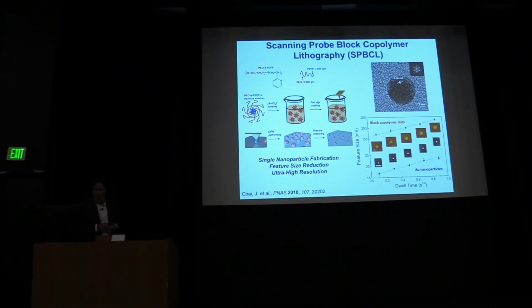If that's hydrophobic, so we can control the type of substrate we use, it will bead up in the form of a reactor that literally has attoliters or less of volume. And then we can treat under reducing conditions, either plasma or heating, as you're going to see, under a hydrogen atmosphere at high temperatures. Blow away the polymer, reduce the metal ions, and if everything works well, all the atoms will come together and form one nanoparticle.